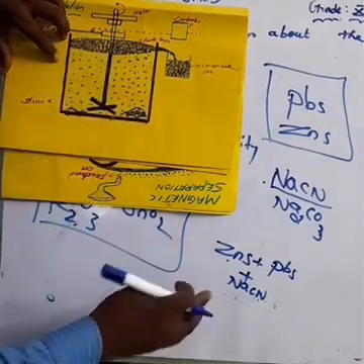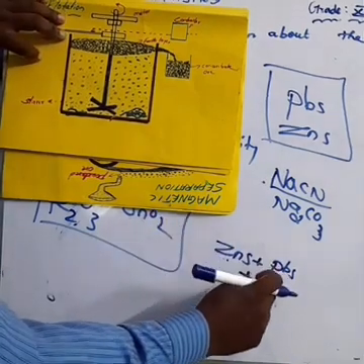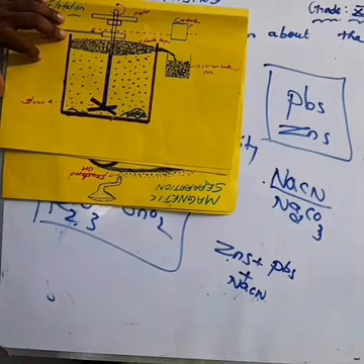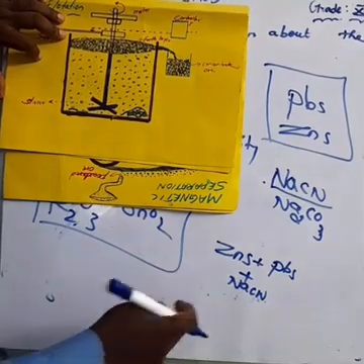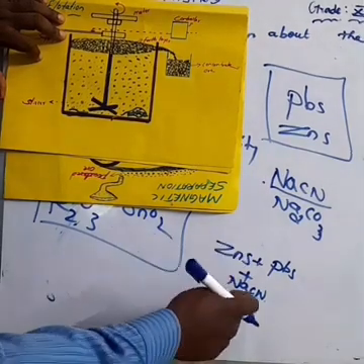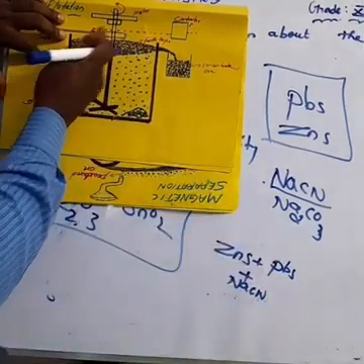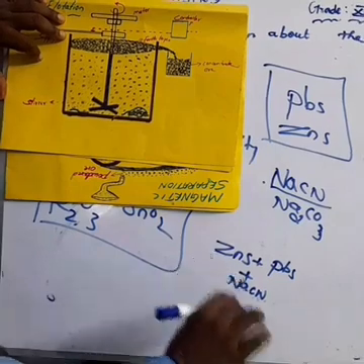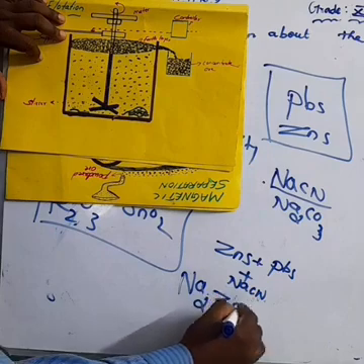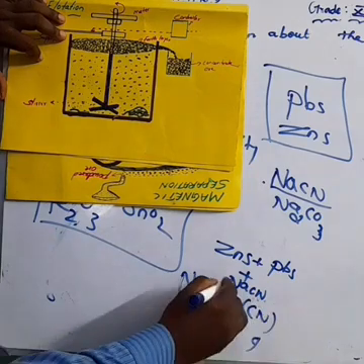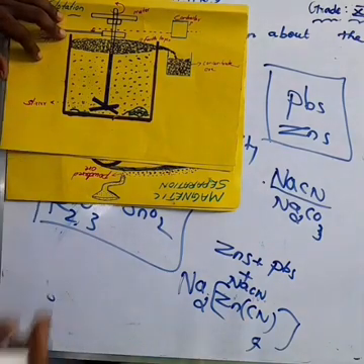When an impurity such as zinc sulfide, zinc blende, is present in galena, we add sodium cyanide to depress the flotation property of zinc sulfide by forming a layer of zinc complex. What is the complex there? Na2[Zn(CN)4], on the surface of zinc sulfide.